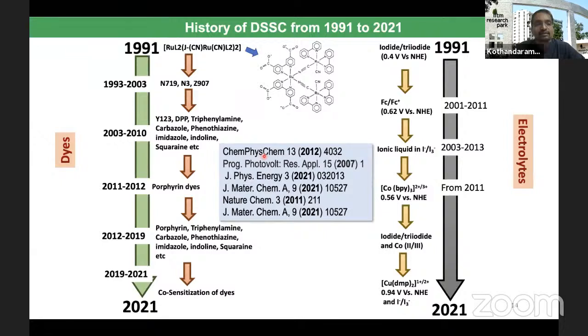So therefore, the efforts are on developing high voltage electrolytes. For example, in 1991, iodide/triiodide was used. It's about 0.4 volt with respect to NHE, but the latest is the use of CuDMP. So this has about 0.94 volt. That means literally about 0.54 volt you can gain using this electrolyte instead of conventional iodide/triiodide.